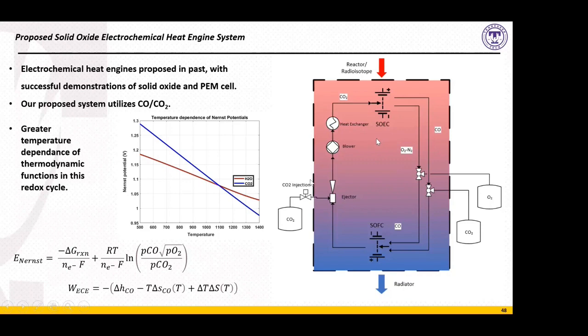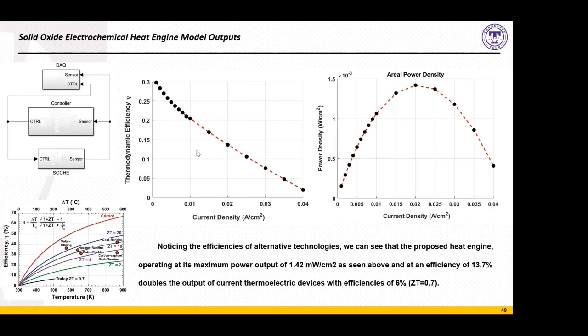For just electrical power output. Now, our proposed system utilizes carbon monoxide and carbon dioxide, because as you can see here, the Gibbs free energy of reaction is more temperature dependent for this redox cycle than it is for the hydrogen steam cycle. And so we have done some steady state analysis on this as well, building a Simulink model to mimic this type of system. And what we find is that for low current densities, we can get power output with a total thermodynamic efficiency of up to 30%.